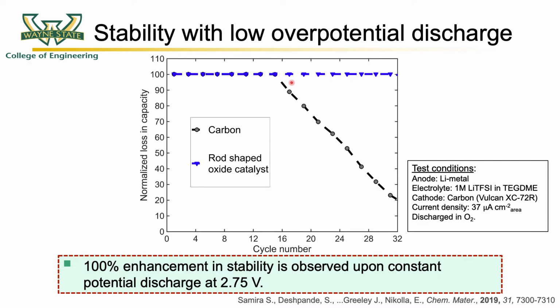With roughly 100% enhancement, going all the way from 16 cycles on a carbon only electrode to more than 32 cycles on an LNO containing electrode.